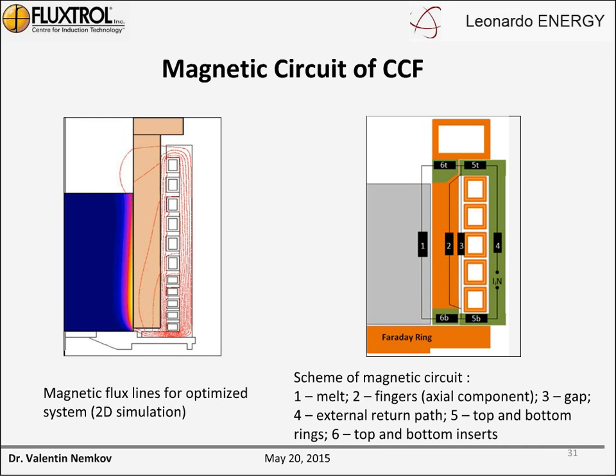It contains portion one, which describes the heating area in the melt. Part two describes the fingers, for axial components of magnetic flux flowing along the fingers. Three corresponds to the gap and four to the return path of magnetic flux. But we also have here two areas, five top and five bottom, which describe the magnetic resistance of the narrow areas between the coil and the bottom Faraday ring, if for this type of induction cold crucible furnace we have this ring, and the top Faraday.